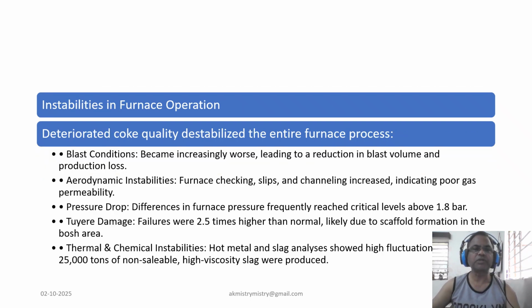This instability was not isolated, it cascaded through the entire operation. Blast conditions became progressively worse, forcing a reduction in blast volume and leading directly to production loss. The furnace experienced more frequent checking, slips and channeling, all signs of poor gas permeability and an unstable burden column. The pressure drop across the furnace frequently hit critical levels, indicating the process was on the verge of collapse. The physical toll was also severe. Tuyere failures, which are costly and disruptive, increased by 2.5 times the normal rate, likely due to scaffold formation in the Bosh area. Finally, the process became chemically unstable with wild fluctuations in hot metal and slag quality. The furnace produced over 25,000 tons of non-sellable high viscosity slag during this period.